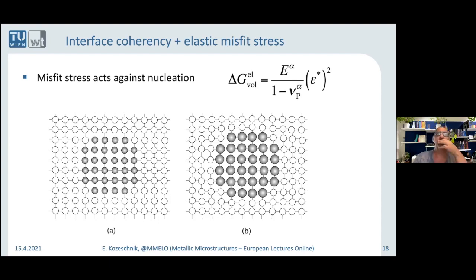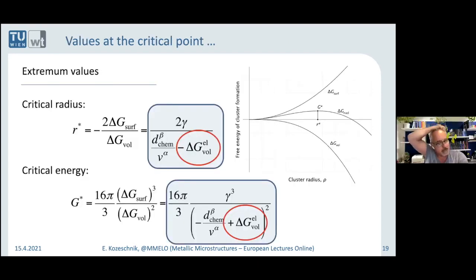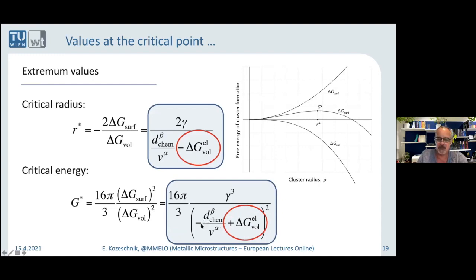In most cases, you definitely have to take these elastic stresses into account, because I think most nucleation processes are more or less occurring in a coherent structure. When nucleation theory is extended, the critical quantities now also add the stress energy, and you can see it has a different sign compared to the chemical driving force — so it's always reducing the chemical driving force and actually increasing the nucleation barrier.